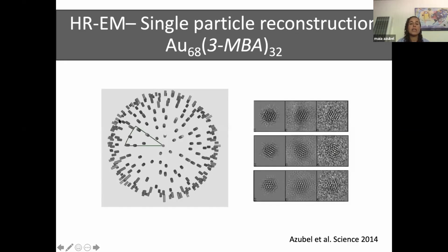So what you are seeing here on the left is the distribution of all these classes that were used to build the 3D structure. And it's very important, each one of these bars, I will tell you exactly what it is, but it's very important that you see that you have coverage of all of this space, because otherwise you will see that there is some part of your particle that has not been imaged, so you don't have the information that corresponds to that view.